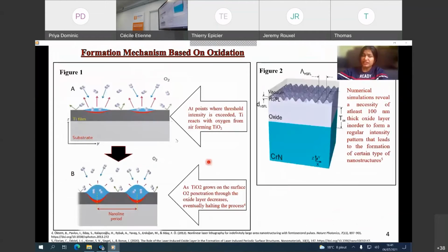And recently, there is another model that explains the formation of the nanostructures based on oxidation. So in figure 1, you can see a titanium film, and according to this explanation, at points where the threshold intensity is exceeded, titanium reacts with oxygen from the atmosphere, forming titanium dioxide. And as the titanium dioxide growth increases on the surface, the oxygen penetration through the oxide layer decreases, eventually halting the process. So according to this explanation, the formation of oxide on the surface of the ripples provides a negative feedback to the overall growth of the ripples, and thereby stops and controls the ripple formation. And in figure 2, you can see the main results of a numerical simulation on chromium nitride that says that you need at least 100 nanometer thickness of oxide layer for the formation of certain nanostructures.